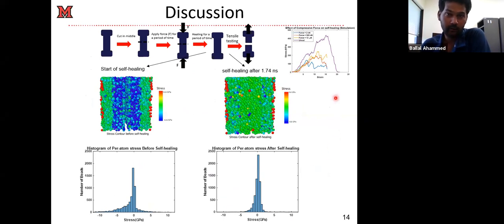So now we'd like to see atomistically what happens when we apply the compressive stresses. When you apply the compressive stresses, just before the simulations, you see there is an accumulation of compressive stresses in the materials. That's very expected. When the self-healing is done, if you look at this contour plot, you see those compressive stresses disappear, and we can see the same thing is happening here.